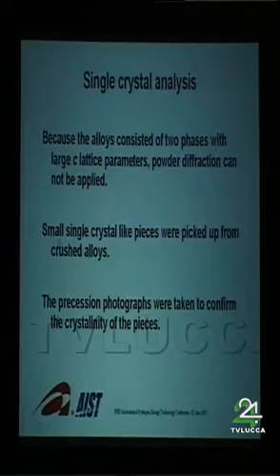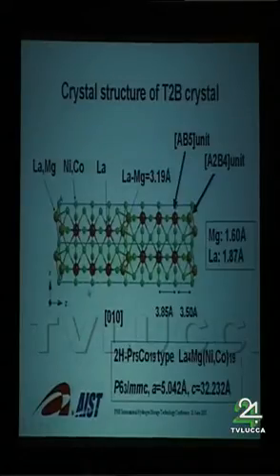So small single crystal-like pieces were picked up from crushed alloys. Precession photographs were taken to confirm the crystallinity of the pieces. So it takes a long, long time. It's very time-consuming, and it's very hard work for the scientists to pick up a very nice piece from the crushed alloys. But anyway, we succeeded in determining this kind of structure.